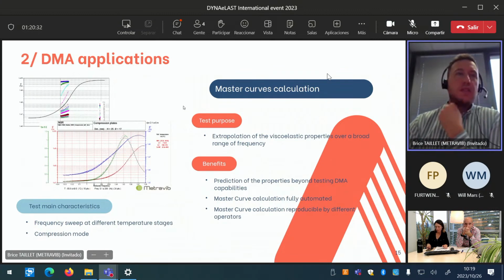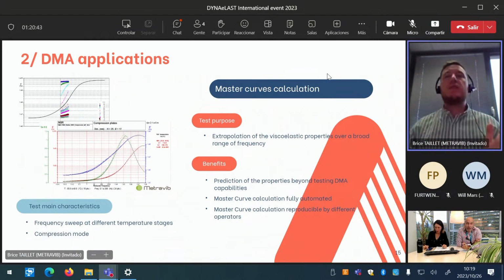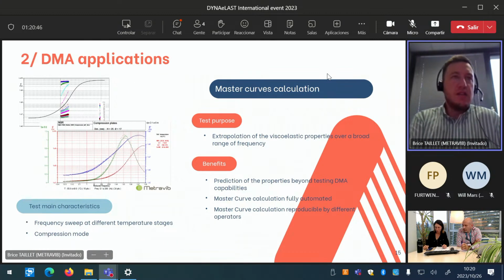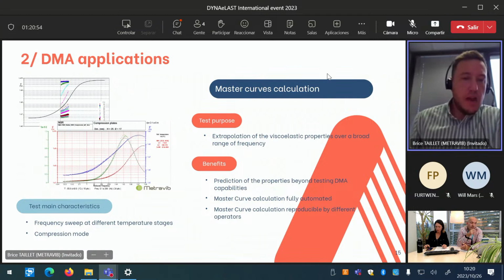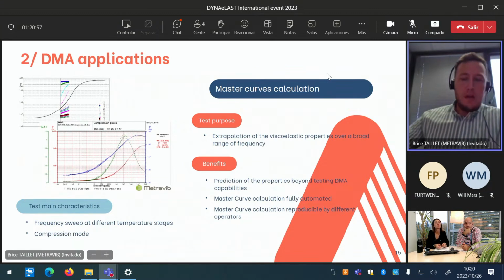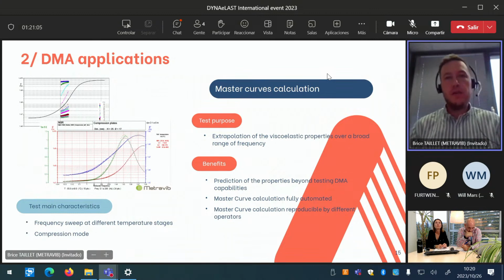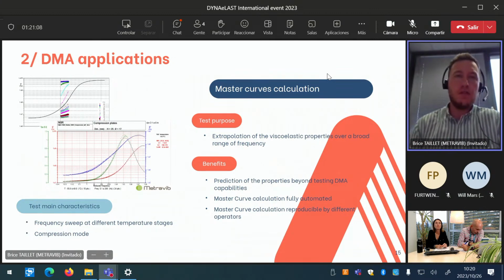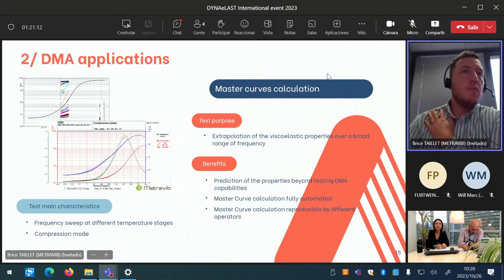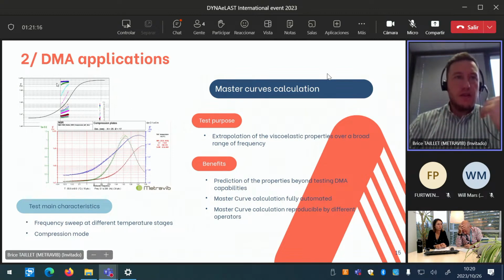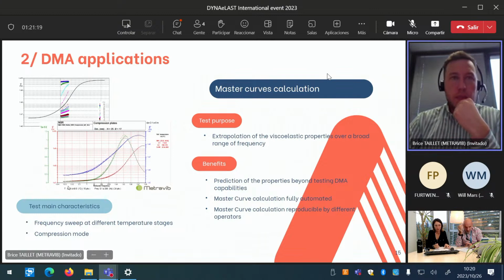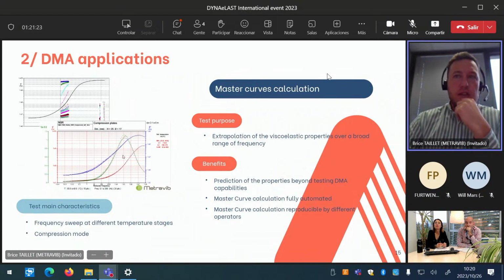One other application, quite important, is the capability to compute master curves. Master curves is just the ability to have prediction of properties beyond testing DMA capabilities. As explained, in DMA+1000, for instance, the maximum frequency we can achieve directly is 1 kilohertz. But sometimes in industrial life, we would like to characterize viscoelastic properties over 1 kilohertz, maybe 10, 20, or 50 kilohertz, for instance. So the only way to have viscoelastic properties for such frequency is to compute a master curve. For a master curve, we just apply some frequency sweeps under different temperature stages, and with some algorithm, we are able to compute this kind of curve.